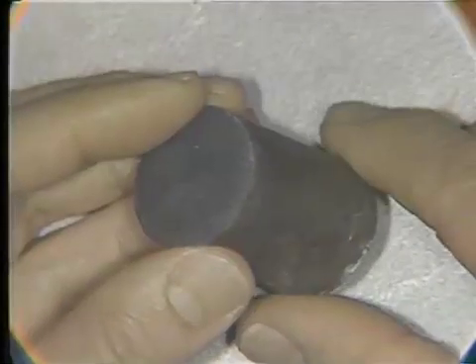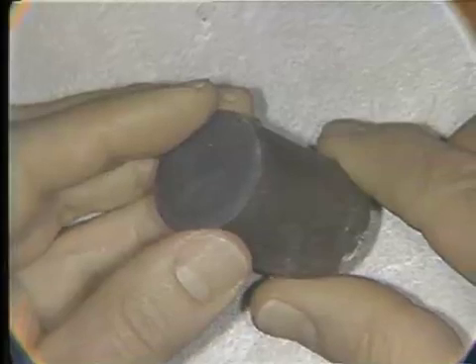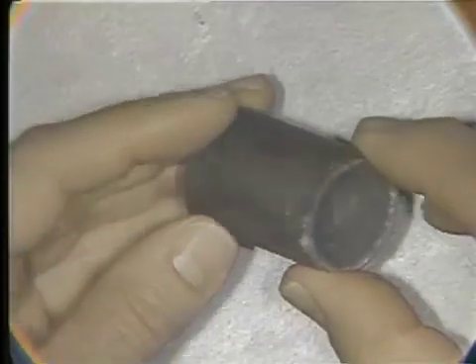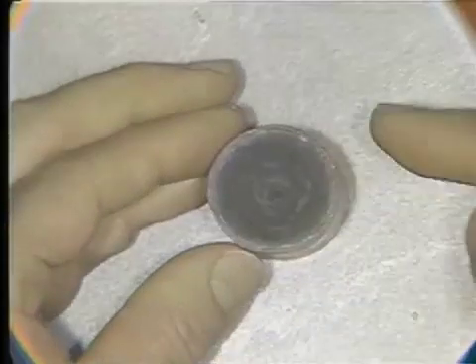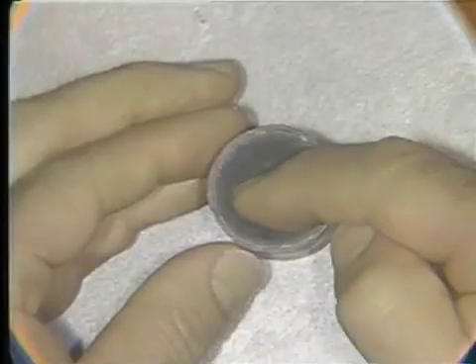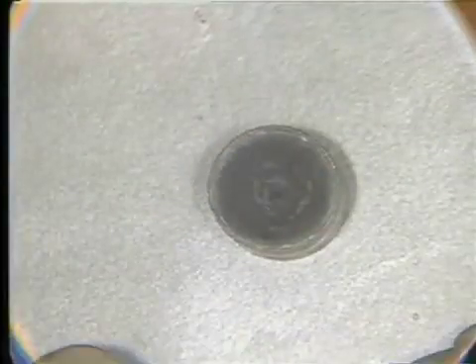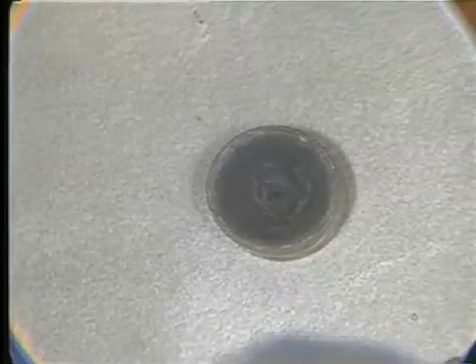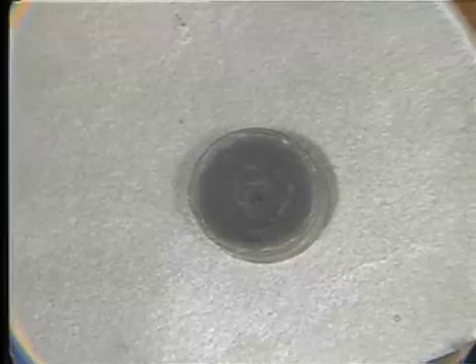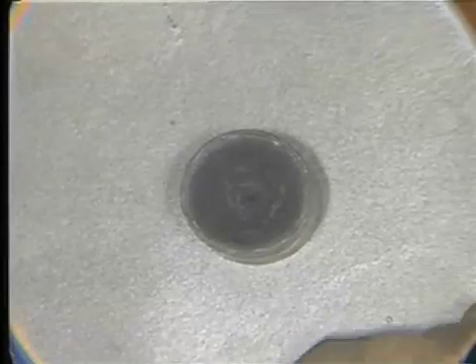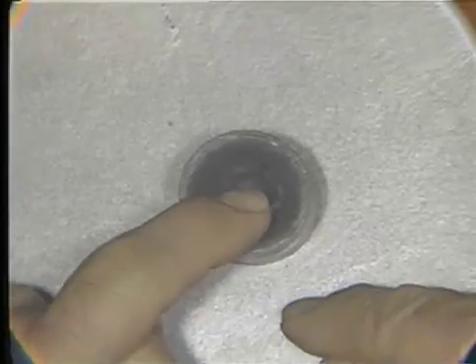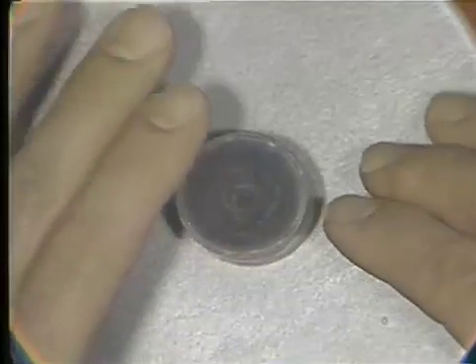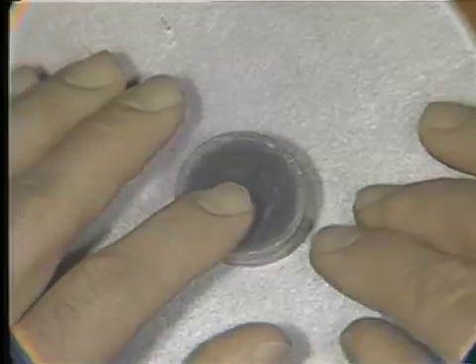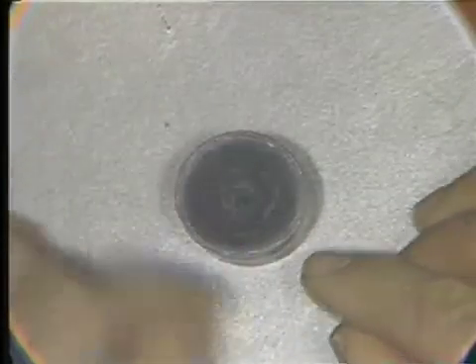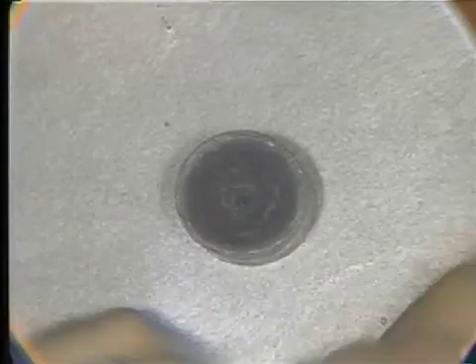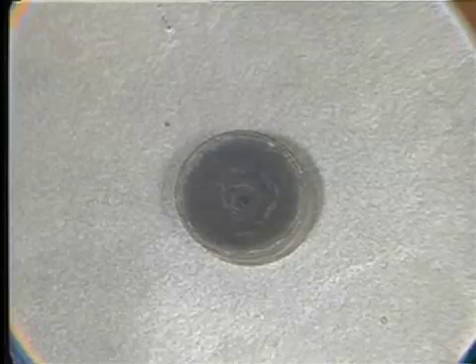And then the small amount of wax that remains in the investment or is absorbed by the investment, you should put the ring up, the hole up, so that oxygen is able to get there and react with the residue of the wax and completely eliminate the wax from the mold cavity. This opens very, very minute porosities of the investment, so that when the molten metal gets in there and pushes the air from the mold cavity, the air is going to go out through the porosity of the investment. And if the wax is not completely eliminated, then that air cannot get out, and one would not obtain a complete casting.